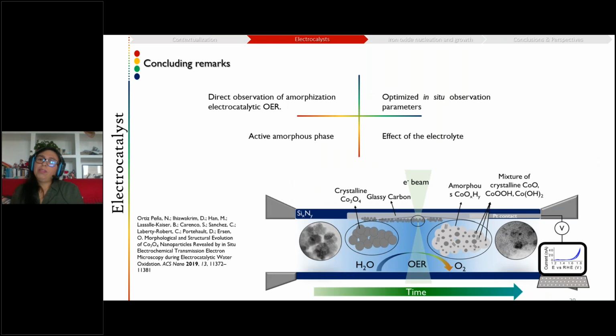So we were very happy to be able to observe directly the amorphization of the surface of cobalt oxide. Of course, all of this required the optimization of the in situ observation parameters. And we think that we point towards the idea that the amorphous phase is probably the active phase, which is not an unknown idea for the electrocatalyst community. And we think that here we show that this might be an activation stage. And we show as well the effect of the electrolyte on the process. This work has been published in ACS Nano.